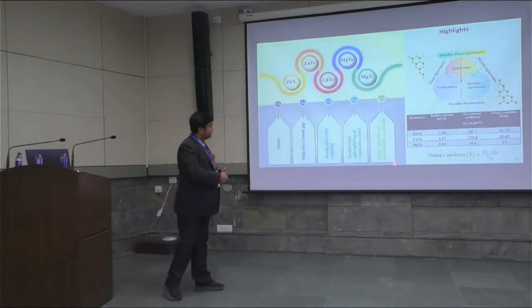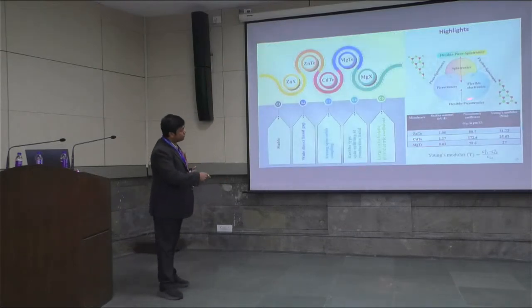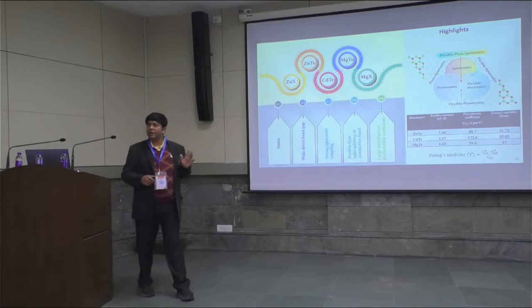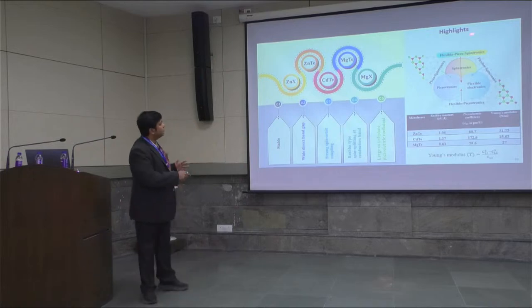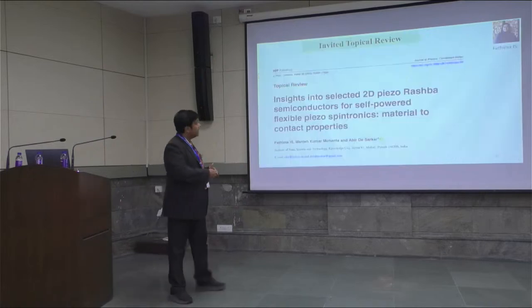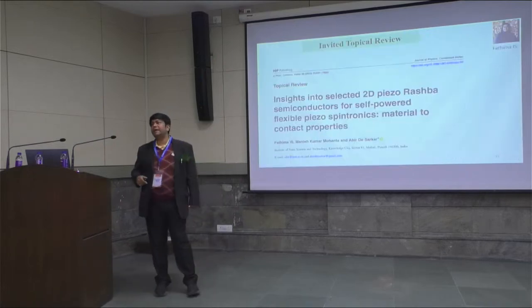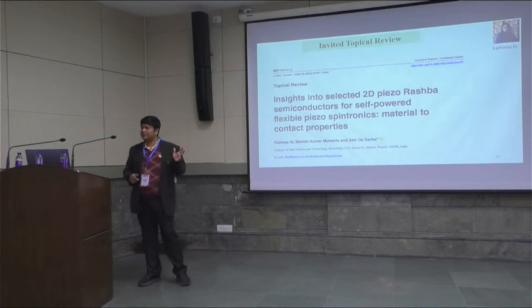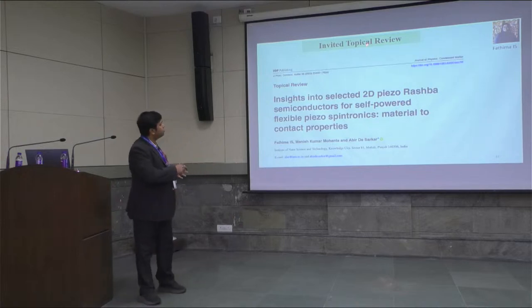So in summary, these three monolayers show a combination of all these three properties. They show a low elastic stiffness constant, so this criterion is satisfied. And they have a high Rashba constant and out-of-plane piezoelectric coefficient. Therefore, we propose that these monolayers will be suitable for flexible piezo spintronics. Our findings and similar findings we have compiled and reviewed in this invited topical review, which I was invited to contribute last year.